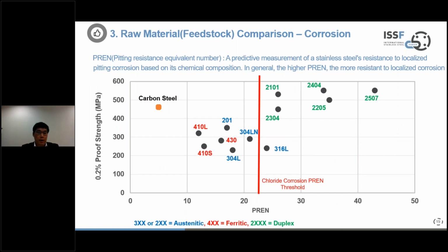Next, for the corrosion part. For corrosion comparison, we're going to use PREN, which stands for pitting resistance equivalent number. Essentially, what it means is the higher the PREN, the better performance it has with regards to corrosion resistance. In the chart below, we can see that on the x-axis we have PREN, and on the y-axis we have 0.2% proof strength. What this means is that this chart places yield strength and corrosion resistance against high chloride environments for grade consideration.